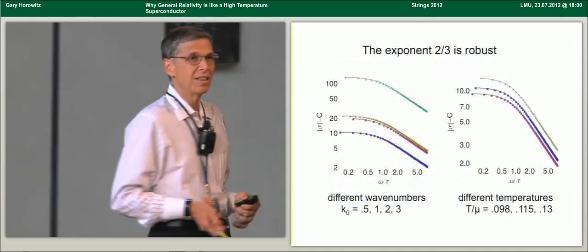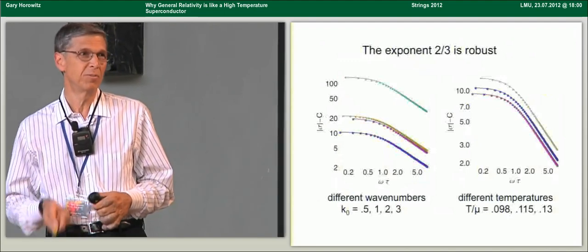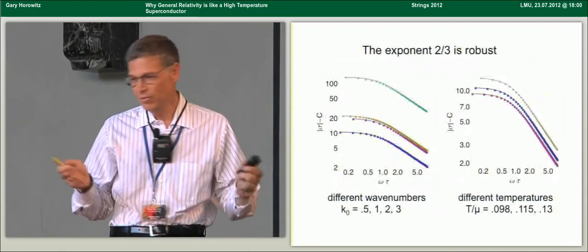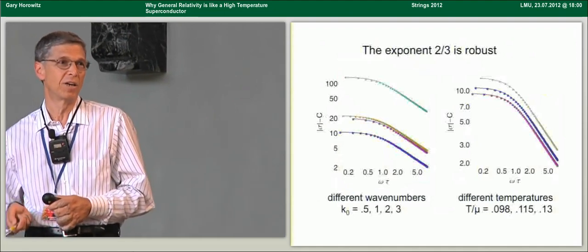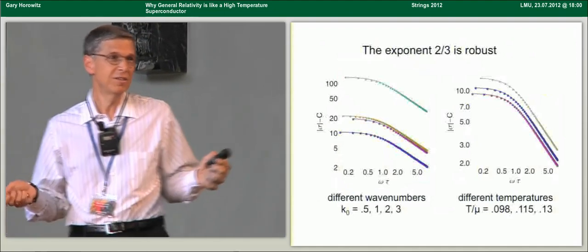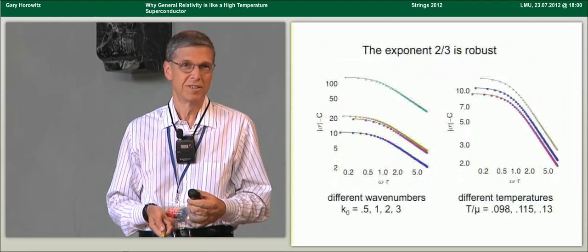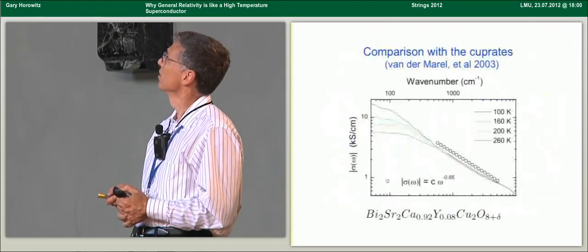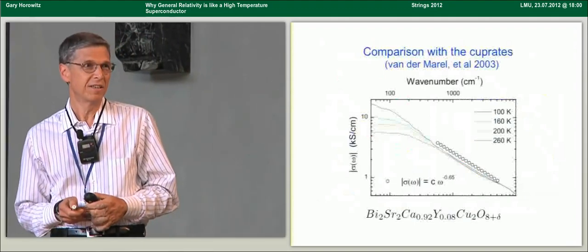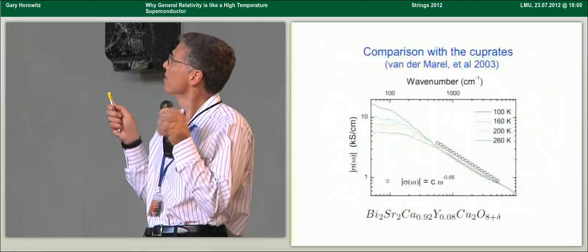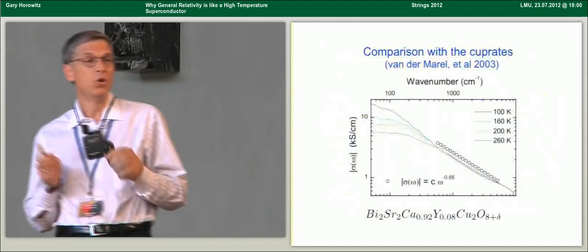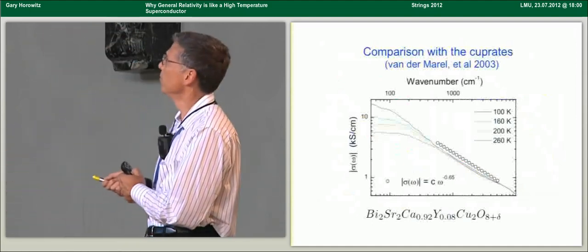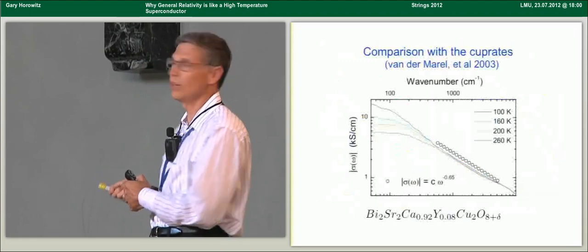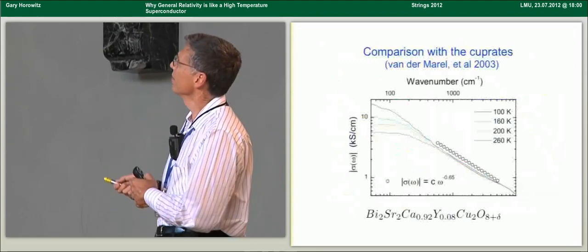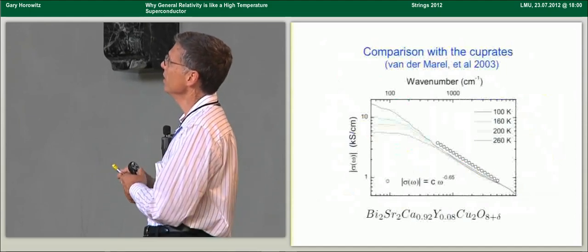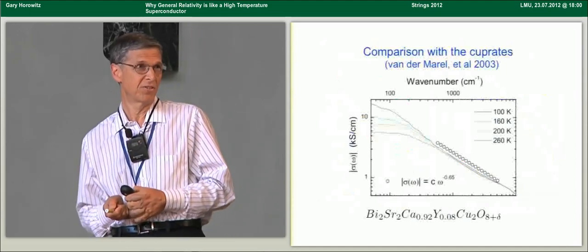Now I told you at the beginning that the Drude model doesn't predict 2/3, it predicts a 1 over omega. And the standard Fermi liquid theory predicts a 1 over omega squared. So have we ever seen 1 over omega to the 2/3 before? And the answer is yes, in nature. Okay, so here's real data. This is data taken by van der Marel and his group on the normal phase of this cuprate, bismuth strontium calcium copper oxide, usually called BSCCO. And here again, they plot the absolute value of the conductivity as a function of frequency for various temperatures.